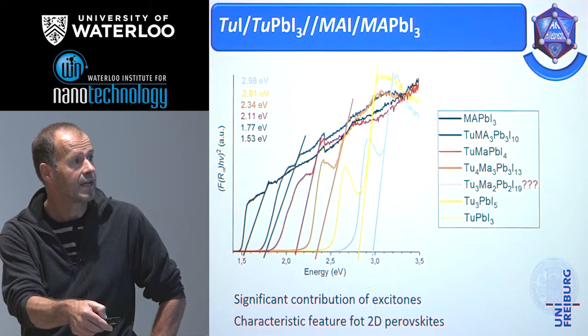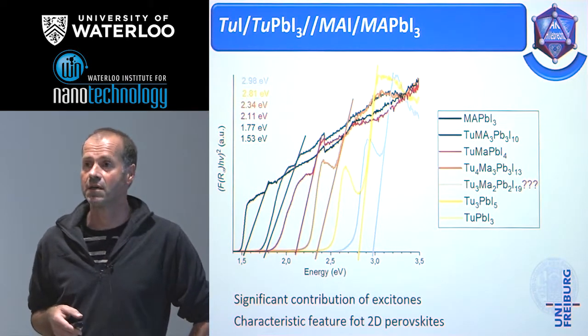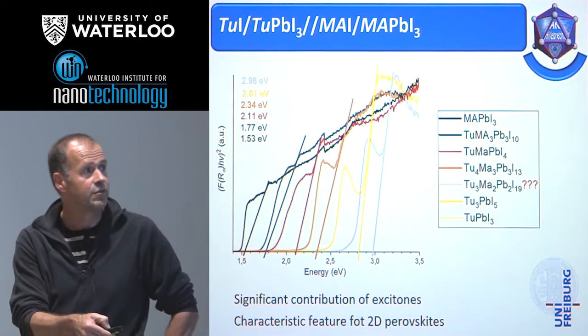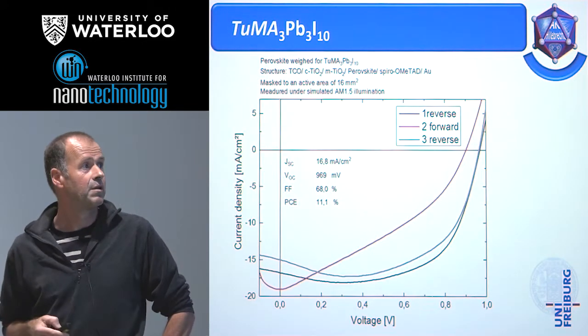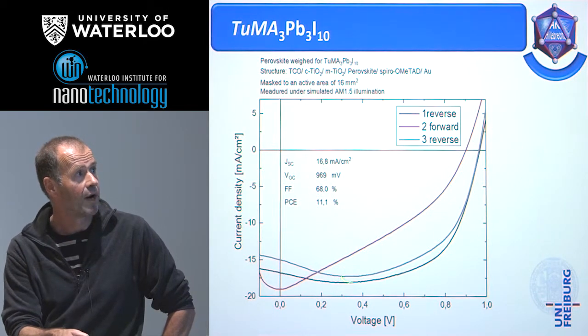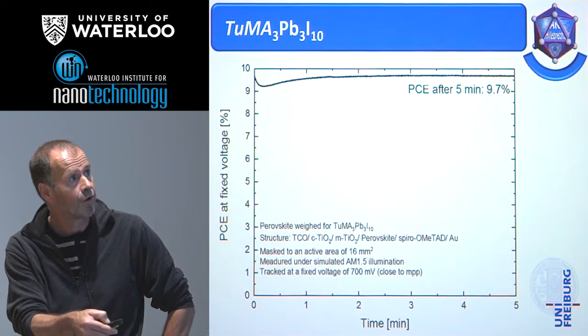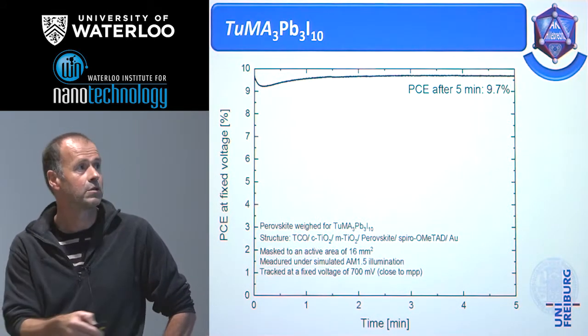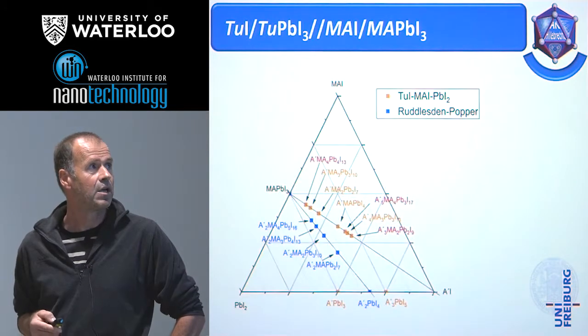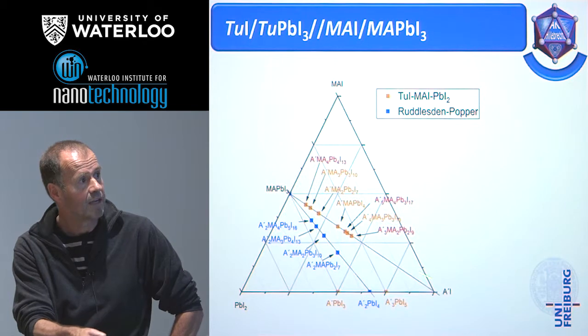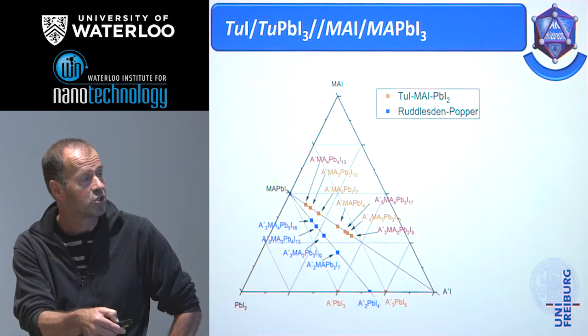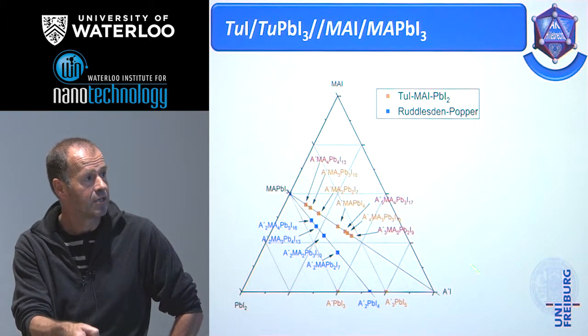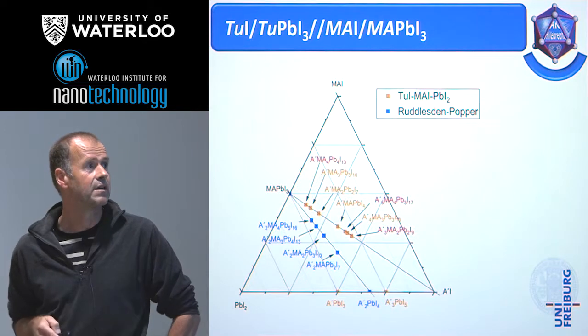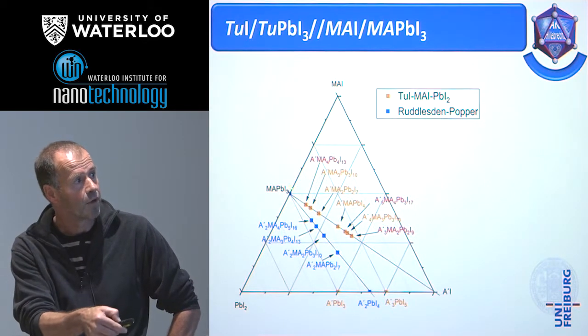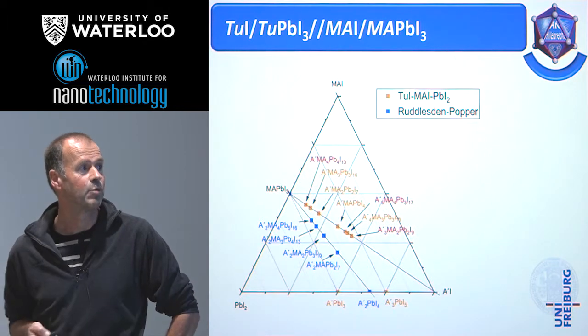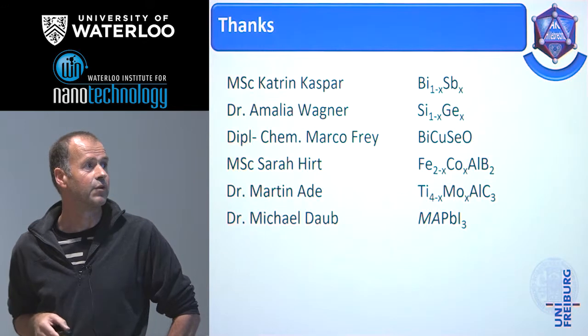And we could show that the band gaps correlate clearly with the share of the edge-sharing octahedra, and we have seen that the excitons, which are an essential property of the two-dimensional perovskites, are also visible in all these systems. So we could build a device with quite good properties, and especially the efficiency is around 10%, and it's a long-term stable compound. We could draw all these compounds in a diagram and show that they are on a line in combination of our cubic perovskite with the additional iodide of the organic cation. So they are on this line, and all the other compounds which are described as derivatives of the Ruddlesden-Popper phases are on another line within this diagram of composition.